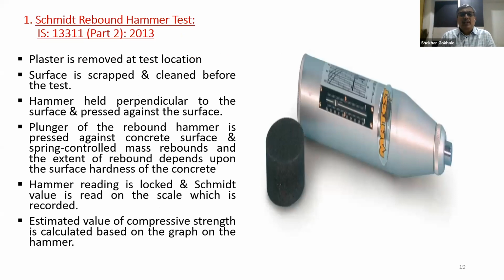This is the rebound hammer test, which has to be conducted on the bare concrete surface, meaning plaster has to be removed before the test, and the surface is scraped and cleaned. The instrument is held perpendicular to the surface and pressed against it, and the spring-controlled mass rebounds, and the extent of rebound gives us the surface hardness of the concrete. The hammer reading is locked when we press the plunger to the surface, and the Schmidt rebound value is recorded on the scale on the instrument. This rebound value gives the estimated compressive strength based on the graph provided by the manufacturer.